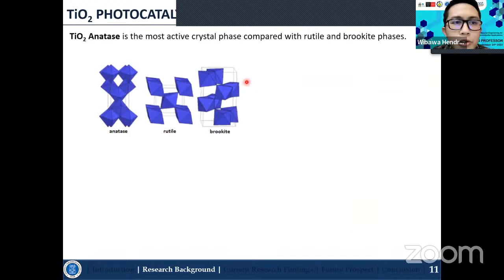TiO2 is one of the most abundant and also commercially available photocatalysts in recent times. TiO2 has three different crystal structures: anatase, rutile, and brookite. From the references, anatase is reported as the most active crystal phase compared with the rutile and brookite phases. But at the moment, the commercially available one is a mixture of anatase and rutile, which we call P25 Degussa, consisting of 80% anatase and 20% rutile. It is reported that this mix of crystal phases is more active compared with anatase alone.